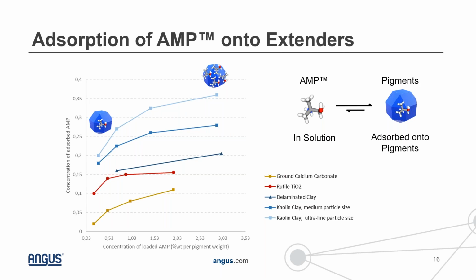This is also the case for extenders as well. This is a very similar type of experiment, where on the x-axis we have the concentration of AMP that was introduced as a weight percent on pigment, and then the determined concentration of AMP that's adsorbed onto the particle surface. If you start at the bottom, we look at calcium carbonate. The line in red is looking at a TiO2, and some of these blue lines correspond to either a delaminated clay or a kaolin clay.